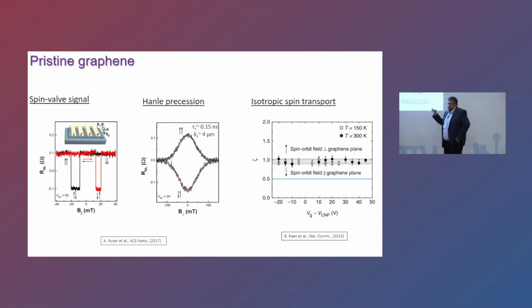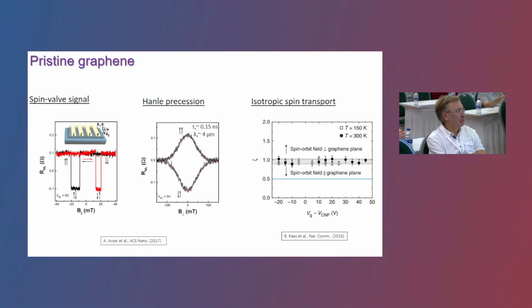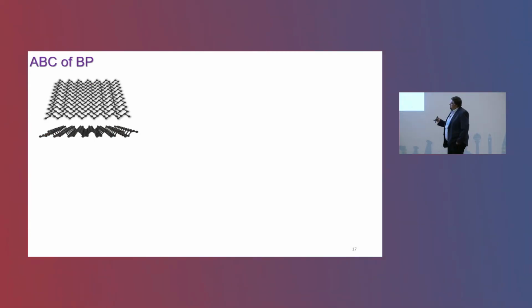Before showing you anything about spin transport with black phosphorus, let me show some example measurements obtained in graphene spin valves. This is a typical spin valve geometry. You have this rectangular-type spin valve signal. This is the Hanle spin precession measurement. The amount of signal that you have is exactly the same as with the spin valve geometry. And also the anisotropy in this material for spins out of plane versus in plane is very isotropic, meaning it doesn't matter if the spins are pointing out of plane or in plane, they have the same lifetimes. I will show you that black phosphorus is different, but let me first introduce these materials very briefly.